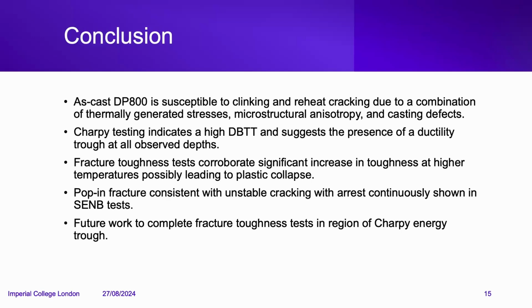And in summary, Charpy testing is indicating a fairly high ductile to brittle transition temperature to be expected with the large grain sizes we see, and fracture toughness tests are corroborating the increase in toughness with the increase in temperature as well.